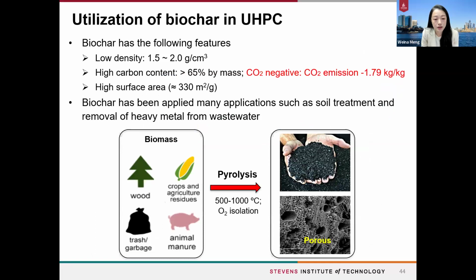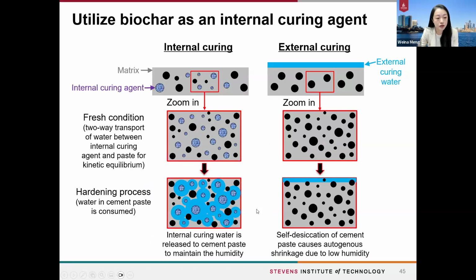The second high carbon type of waste we considered is biochar. Biochar is produced through the pyrolysis process of biomass. It has very similar features to the OSFA: very low density, very high carbon content, and very high surface area. And because of the high carbon and high surface area, it is usually used as a soil treatment material or to remove heavy metals from wastewater. We looked into the microstructure of the biochar and found it's highly porous. So we're thinking to utilize this type of waste as an internal curing agent.